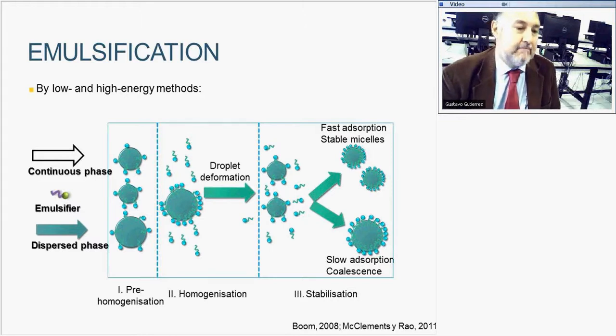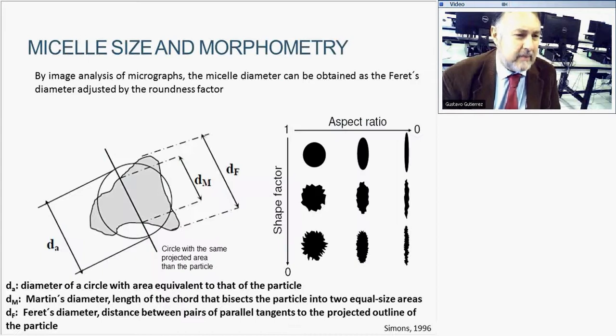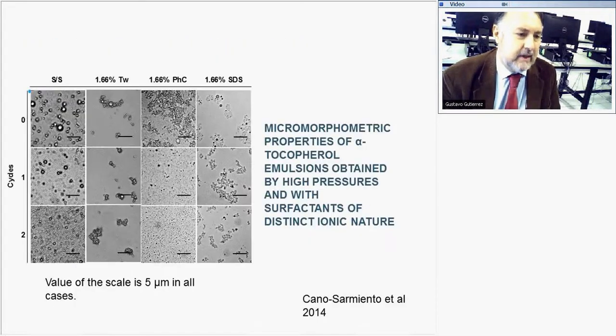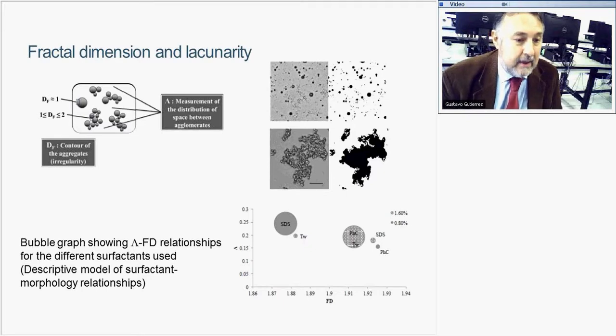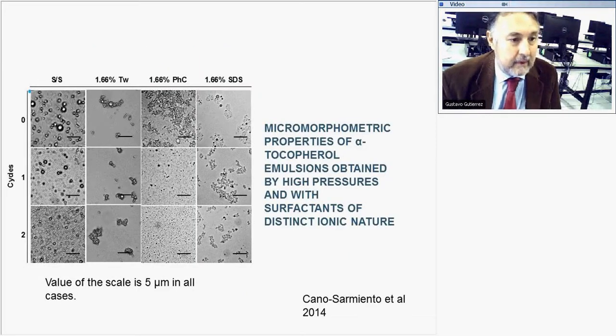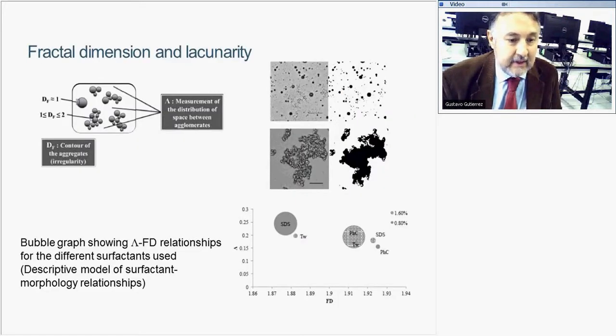We have been doing works on detection. Agglomerates of an emulsifier and tocopherol obtained at high pressure and with these surfactants. What we can see is that the agglomerates could define clusters, and so we get different clusters, which we can generate with a fractal dimension, so we can group by the type of surfactant.